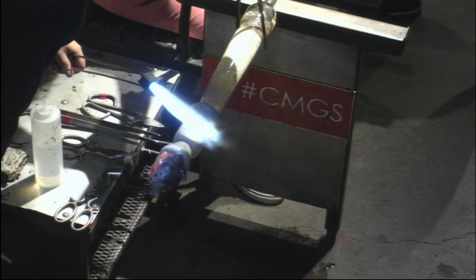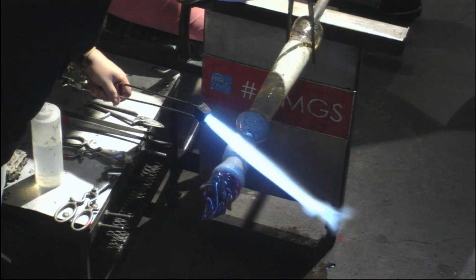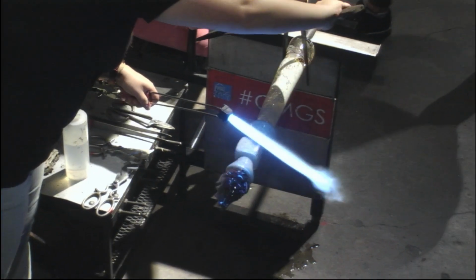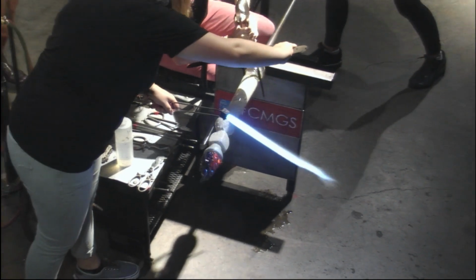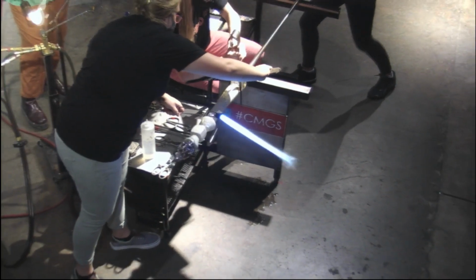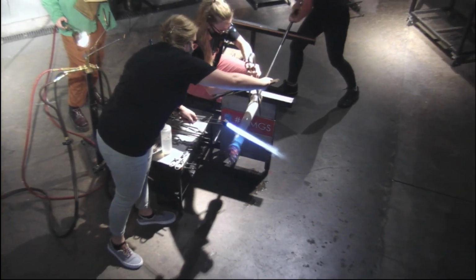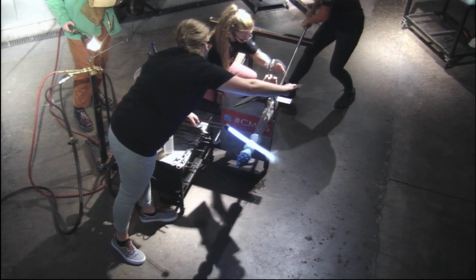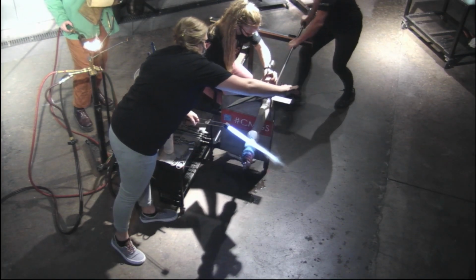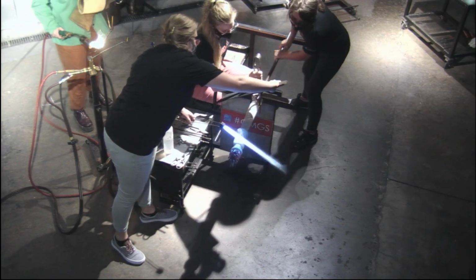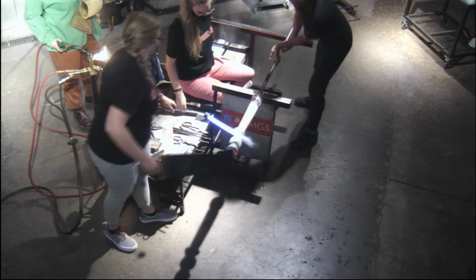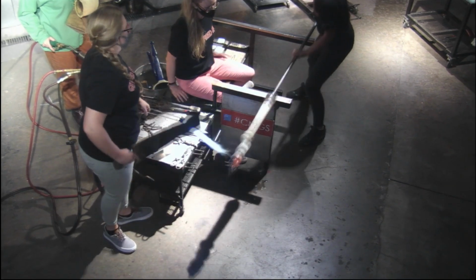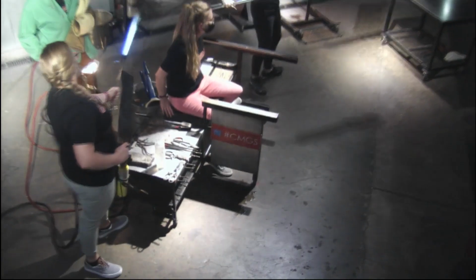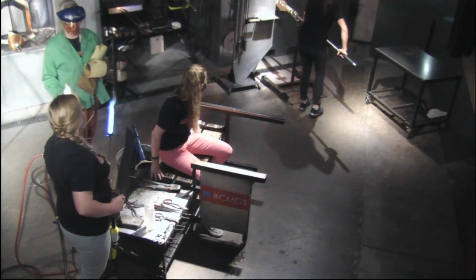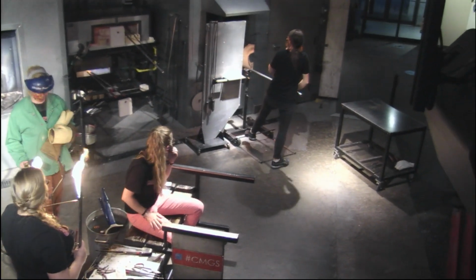So we saw the figurative passing of the torch, but someone's actually going to put gloves on and catch this torch in their gloves and race it back to the kiln. The kiln is sitting at 950 degrees Fahrenheit. And a piece like this, made of solid, thick glass, we're going to cool off for about 24 to 30 hours to remove all the stress and let it be happy with itself. Keep it from cracking. The thicker the glass is, the slower that cooling process needs to be.